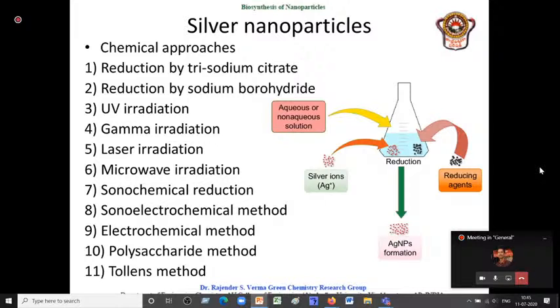In the sense, if you are using a chemical method, well, by the time you turn to a biosynthesis, you should understand what is that chemistry that is responsible for converting a metal ion into a metal nanoparticle, or what is that that is present in the biomolecule or the bioextract, which is responsible either for reduction or for oxidation. So we have chemical methods where you take trisodium citrate and then you can reduce metal ions into metal nanoparticles. Sodium borohydride is one of the strongest reducing agents that we are using.